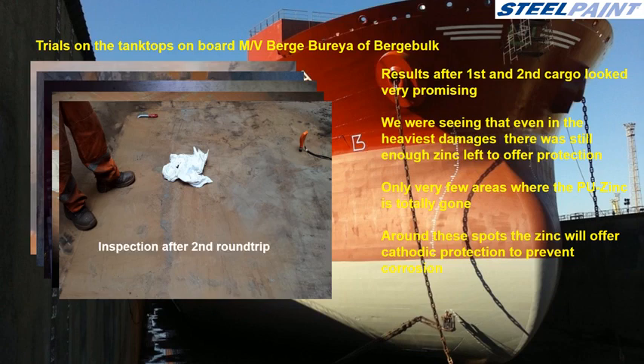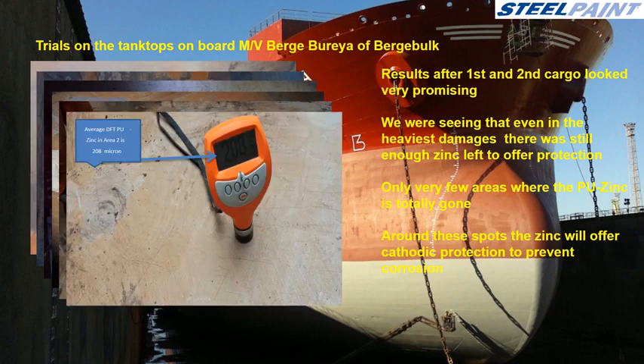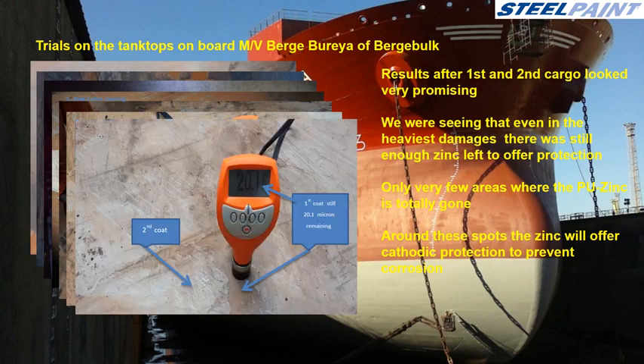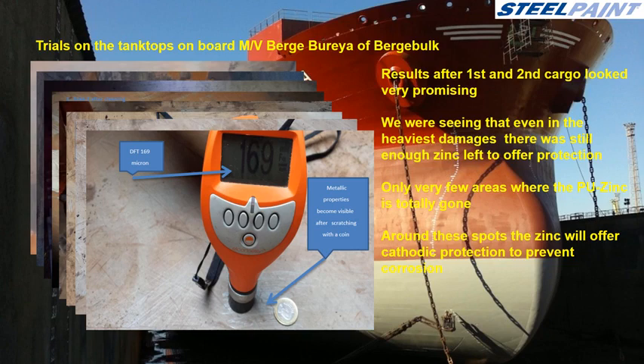These pictures show the results after the second round trip. The average total film thickness is around 200 microns. Even in the damaged areas we can still find zinc. Here we see that there are still 20 microns of zinc left on the substrate. Here we see that the dry film thickness is 169 microns. And after scraping with a coin you can see the metallic action of the zinc quite clearly.